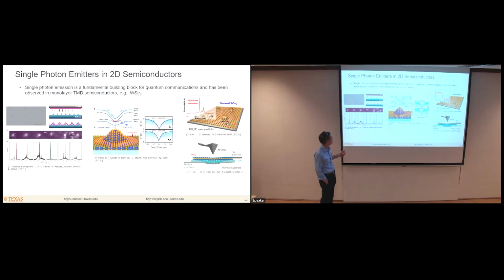And essentially what's done here is the following. This has been observed in a number of different monolayer transition metal dichalcogenide materials. And the most common one for this application is tungsten diselenide. So that's the one that I'll focus on here today. And this behavior of single photon emission arises when one has these materials with highly localized regions of tensile strain. So just stretching the lattice a little bit.